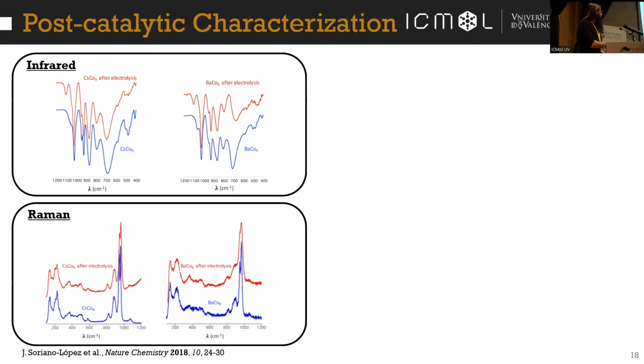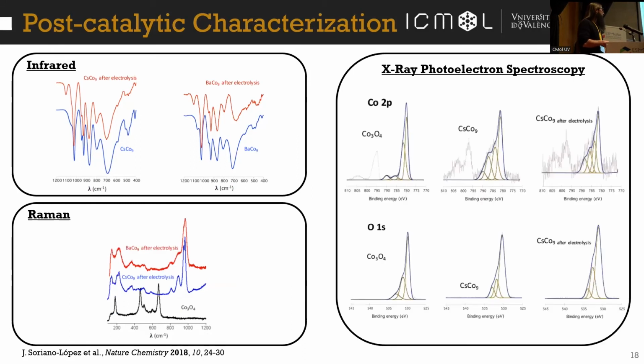And also if we compare it with the cobalt oxide, we see that there is no trace of cobalt oxide. And finally, XPS, again, is very useful for identifying the oxide formation. And here we can see that the polyoxometalate is the same, and also we don't have any oxygen value coming from a lattice oxygen, which should appear below 530 eV.